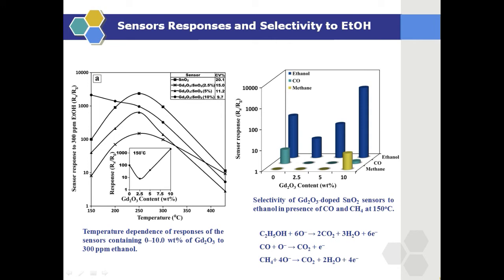Doping gadolinium oxide to tin oxide probably causes some changes in the defect chemistry, which results in high surface activity and a strong interaction between ethanol and surface active sites. Based on high-resolution TEM result, the gadolinium oxide in excess of its solubility limit forms crystallites between tin oxide grains, which are sites for redox reactions.